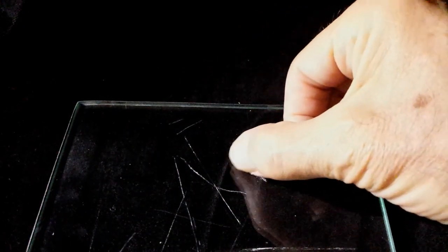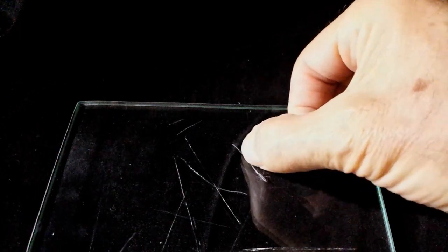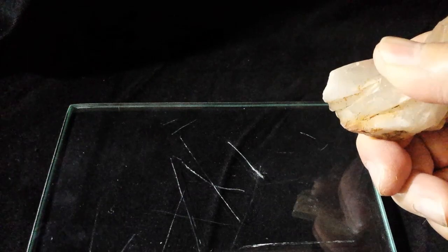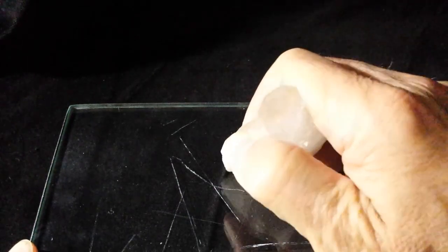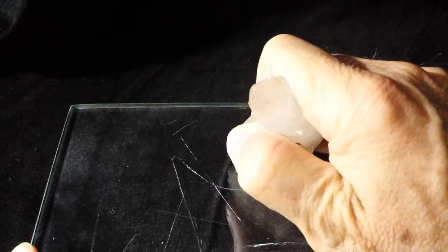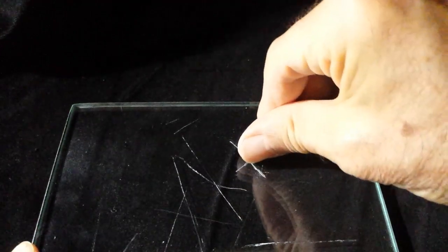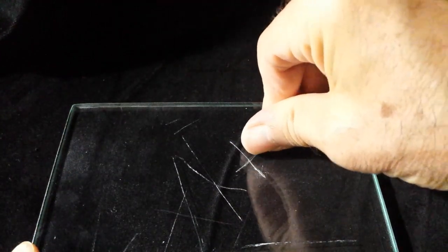Then you must test what looks like a scratch. For that, you drag a fingernail or hard object across the line. If it's really a scratch, you're going to feel the indentation into the glass plate. If it's just a line of crushed powder, you won't feel an indentation.